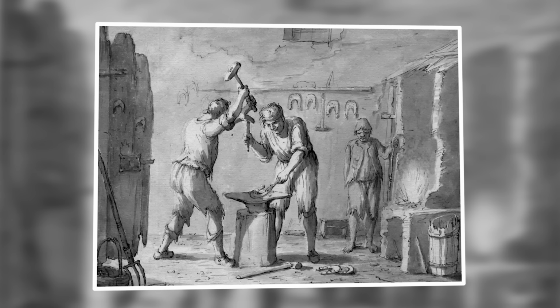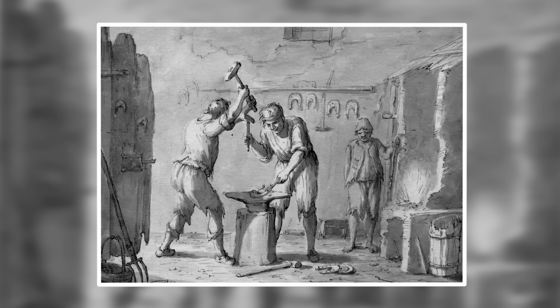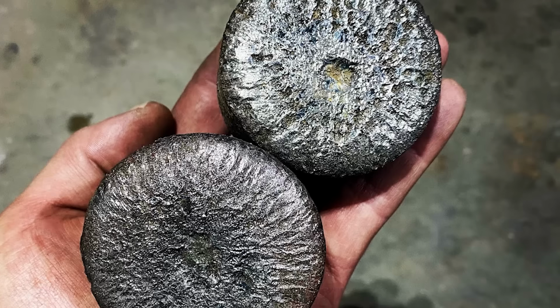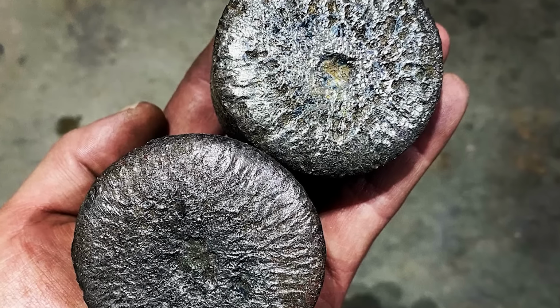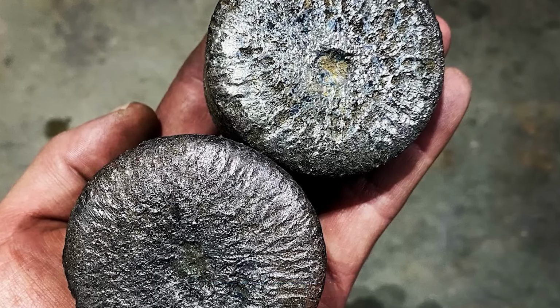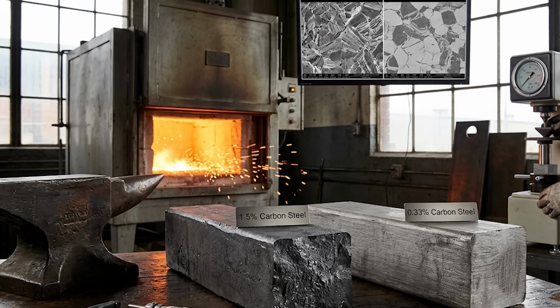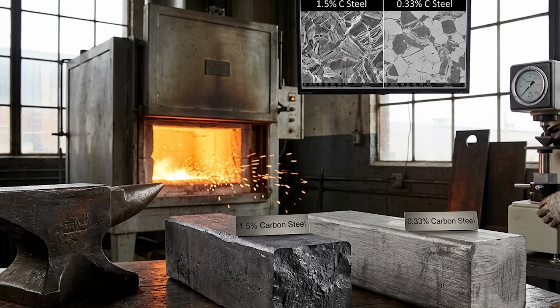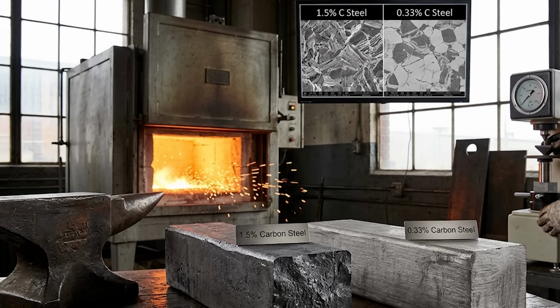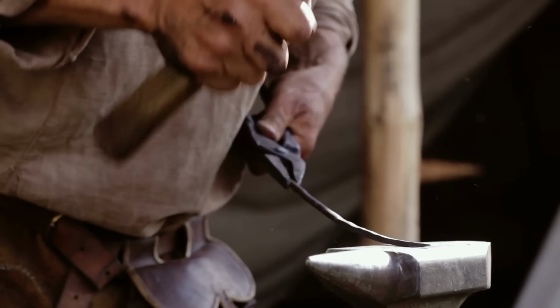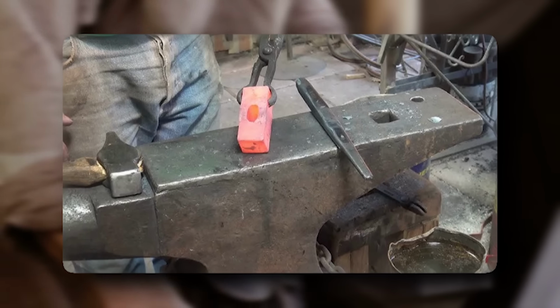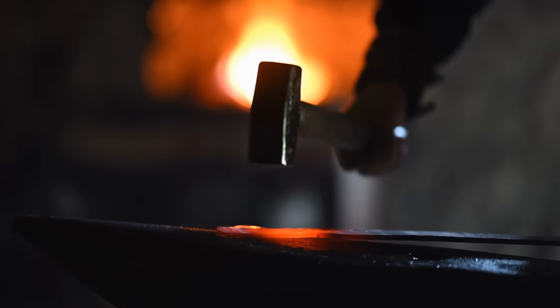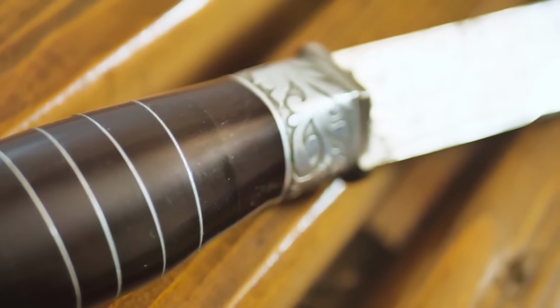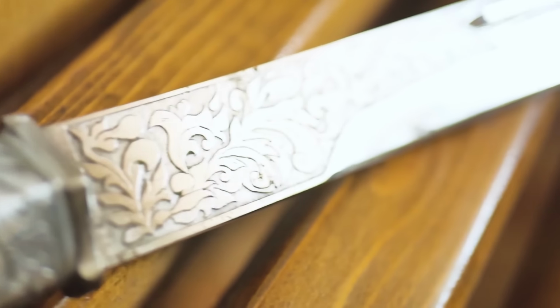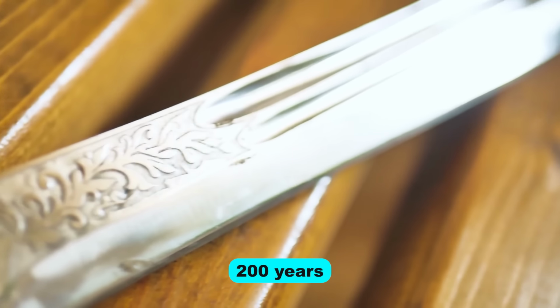Carbon. Ordinary bloomery iron, the kind European blacksmiths worked with for most of the medieval period, contained less than 0.5% carbon, whereas Wootz contained between 1 and 2%. That difference is enormous because carbon is what makes steel hard, and steel with 1.5% carbon is far harder than steel with 0.3%. On the other hand, the harder you make steel, the more brittle it becomes, meaning steel that hard should shatter on impact like glass, and a sword made from it should snap the first time it hits a shield. Wootz, however, did not shatter, and this contradiction mystified every scientist who studied it for 200 years.